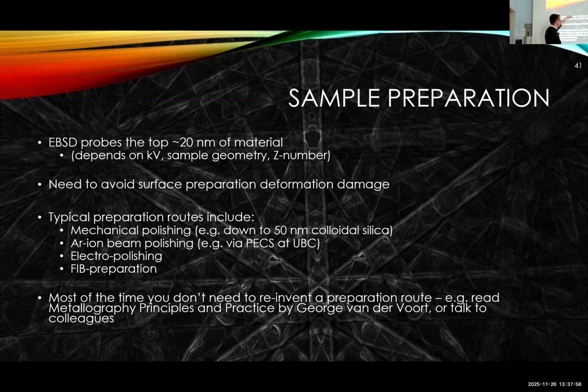This is important because EBSD is about the top 20 nanometers. Actually, as we go down to, say, 8 keV EBSD, it's even smaller. It's dependent on the sample geometry and the Z number of the material, but it's very surface for a technique. So an oxide layer, a deformed smeared surface, or carbon on the surface can mess up what you're doing. So we really want to avoid surface preparation damage.